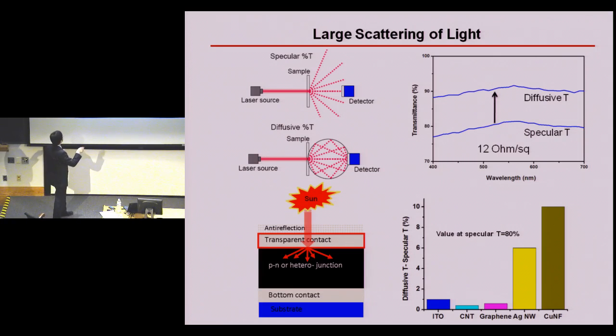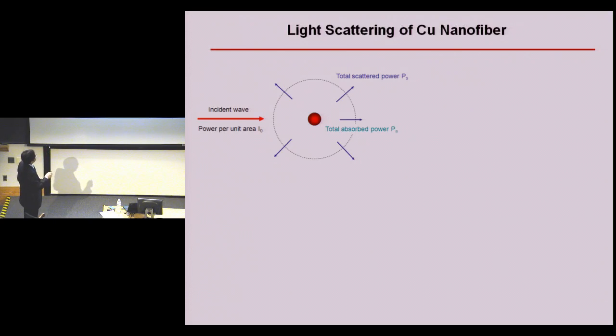The reason follows. So in a real solar cell application, you have this transparent electrode. Once the light is scattered, you will have a longer travel distance in the active layer. So this means you will enhance the absorption of the light inside the active layer. So that will be very beneficial for solar cell application. So this is the comparison of the difference of the two transparency measurements for various kinds of transparent electrodes. For ITO, carbon nanotube and graphene, you see here the difference is very small. But for metal nanowire or carbon nanofiber-based transparent electrodes, the difference is much bigger, which is very beneficial for solar cell application.